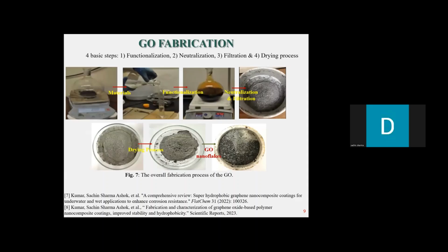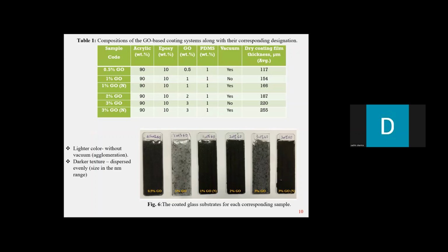Okay. So this was the GO fabrication that I had talked about earlier, and this is a newly invented method by myself, and it's in the process of being patented. And now this is where I stopped. So this is Table 1, which illustrates the compositions of the coating systems that were prepared along with their corresponding designation. In this approach, I used acrylic resin and epoxy resin. There are 2 types of resins over here in the ratio of 90 to 10 weight percentage, and this was kept consistent for all the sample preparation. The only thing that was varied in this experiment was the inclusion of the graphene oxide nanoparticles in increments of 0.5 up to 3 weight percentage.